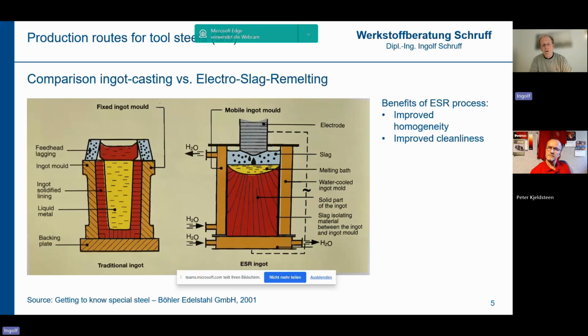solidification is not completely homogeneous. We still have some macroscopic and, of course, microscopic inhomogeneities in the ESR ingot, but in order to further reduce the microscopic inhomogeneities, we do this diffusion annealing, so that with the help of the diffusion process, we can reduce the intensity of microscopic inhomogeneities.